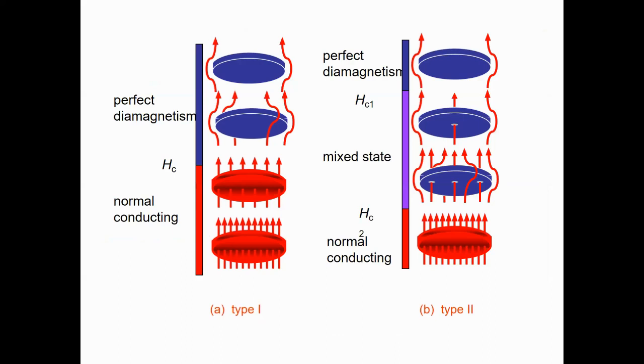Let me tell you the mechanism behind this. There are two types of superconductor, type 1 and type 2. Type 1 superconductors are not usable because the critical field is too low. The superconductivity is broken at very low field. Most practical superconductors belong to type 2. In type 2 superconductors, in the medium field, the superconductor allows penetration of the external magnetic field. With this mixed state, the superconductivity can survive up to very high fields, like 100 Tesla. That means engineering application is possible.